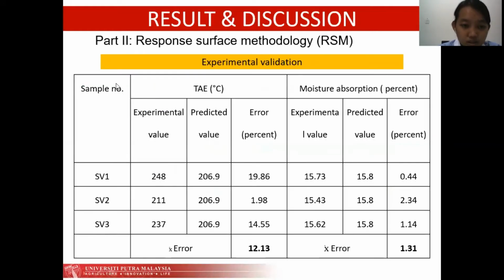Next, this table shows the experimental validation when the composition of the sample is according to the optimal composition. The average error is below 15%, which means that the regression model developed was able to optimize the value for the response accurately.